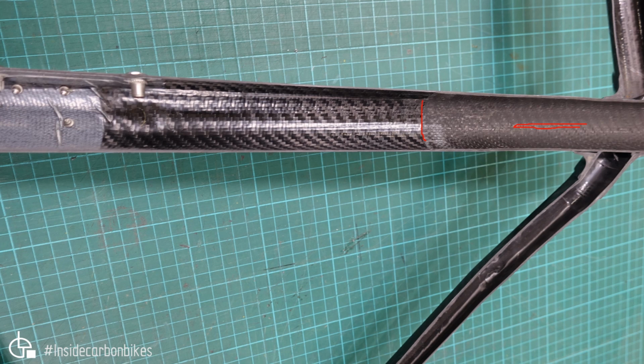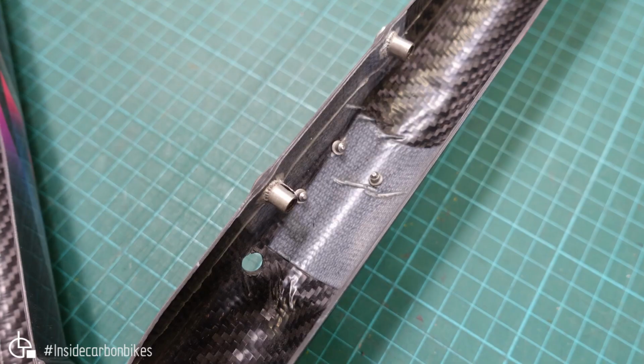Yeah, the rest of the tube looks quite good. You've got a glass barrier ply where the front derailleur hanger sits, using these nice Bigfoot rivets. The glass does just miss. You can see the glass ply ends there, and the rivet is half on carbon, half on glass for both of that one and that one. So that could be in a little bit better spot.